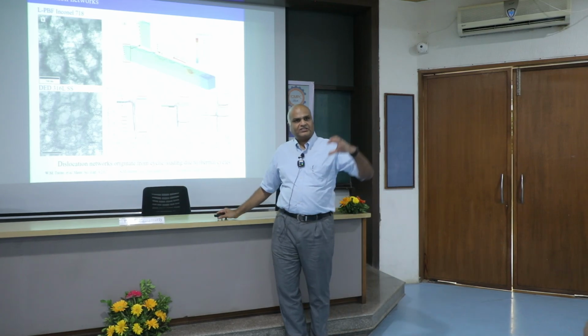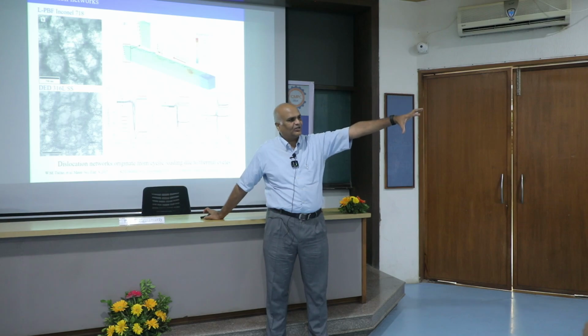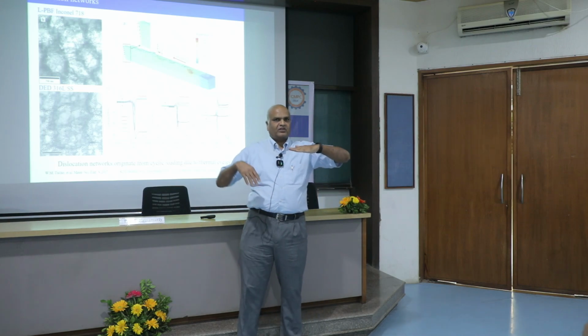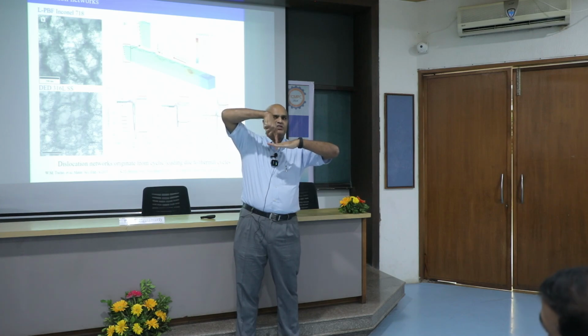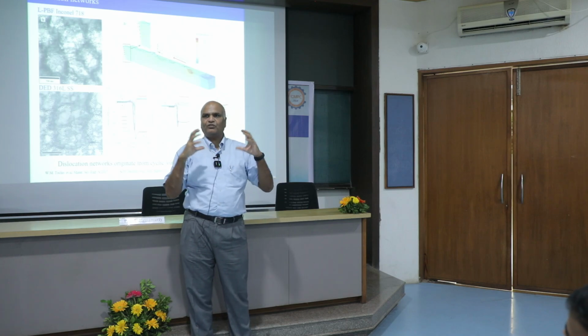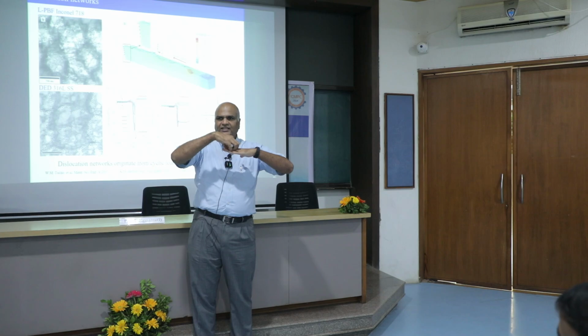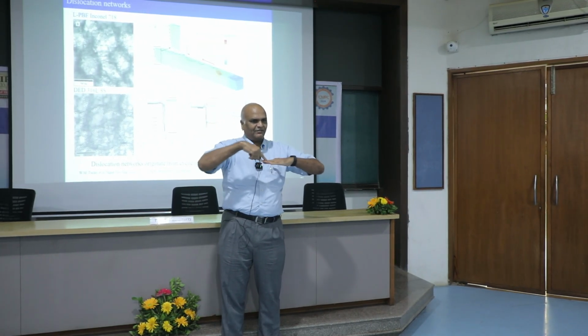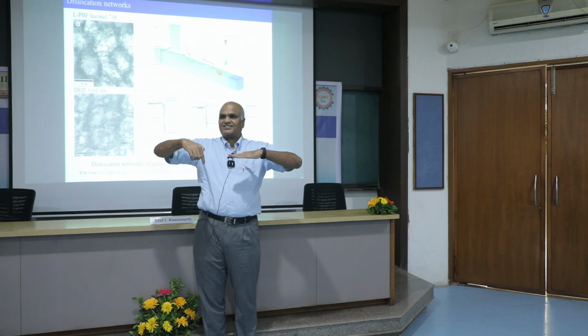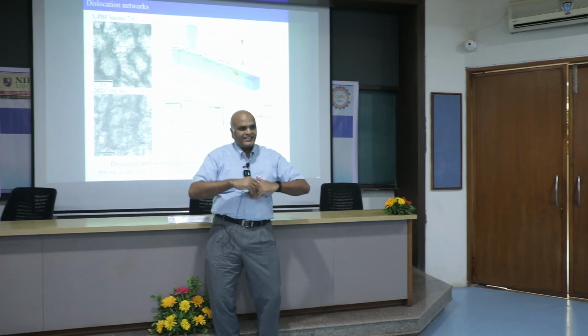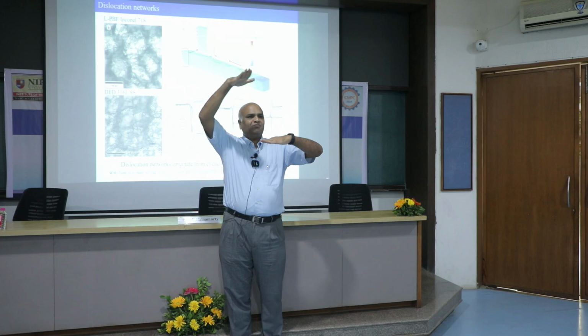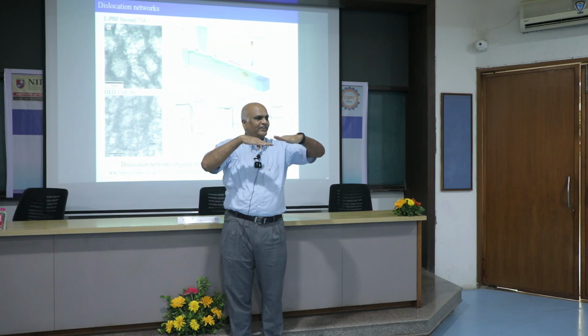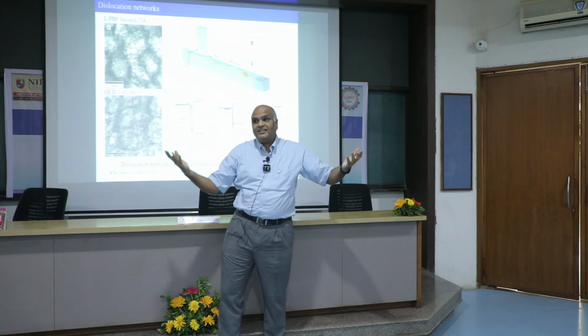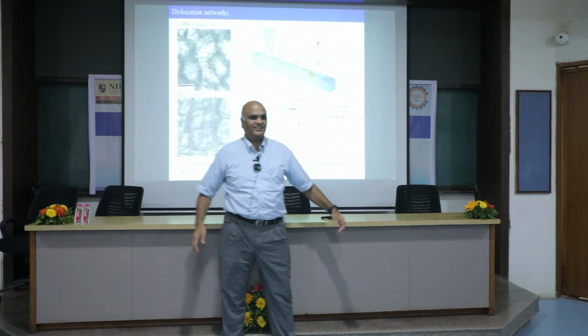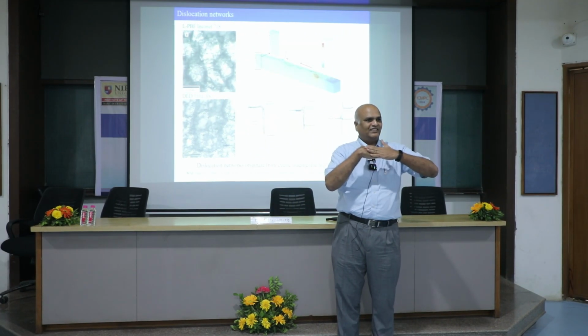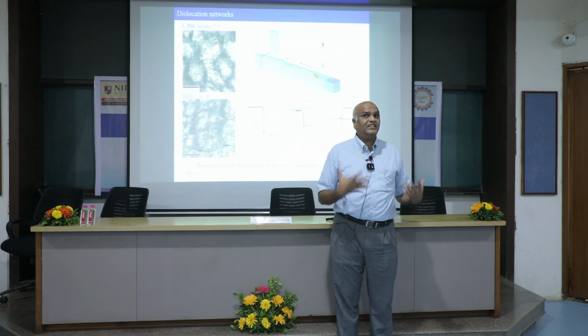You change the process: it's the same alloy, conventionally manufactured, you get one kind of microstructure, one kind of dislocation density. You change here, right? So what are you doing? You are bringing a laser, and at any instance you are melting one voxel, not a pixel, a volumetric cell. You are melting it, it solidifies, and you melt the next, line by line, line by line. When you scan the next line, the already solidified line material gets heated up and cools down. Then you deposit another layer, and this layer that is already cooled and solidified gets heated up and cooled down again. But it can't expand and contract freely on its own, because it's constrained by the substrate. It is stuck to the substrate, so it undergoes thermomechanical cycling, some serious thermomechanical cycling.